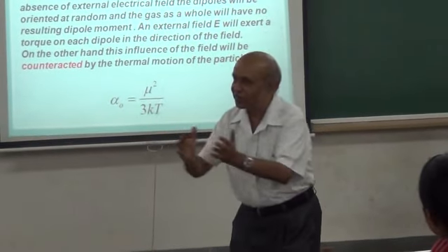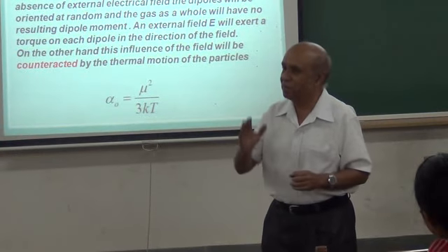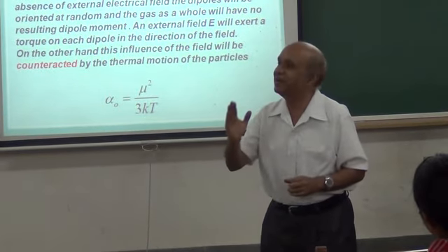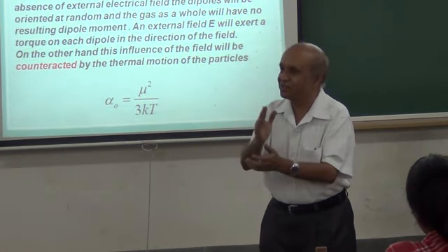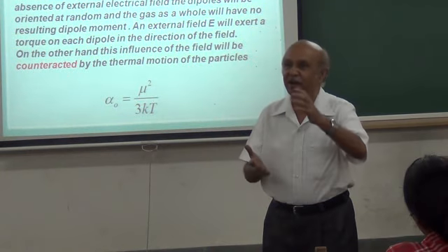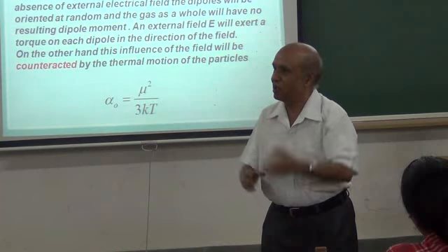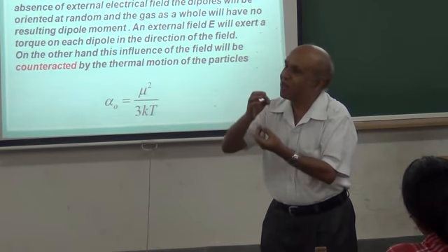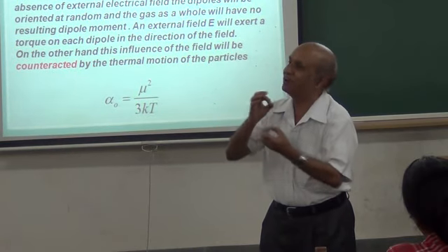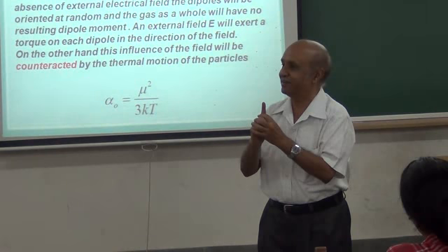But if you cool this crystal below a characteristic temperature of 120 degrees Celsius, the structure gets distorted to a tetragonal type. Then you will have a displacement of the positive and negative charges, which gives rise to a characteristic dipole moment.